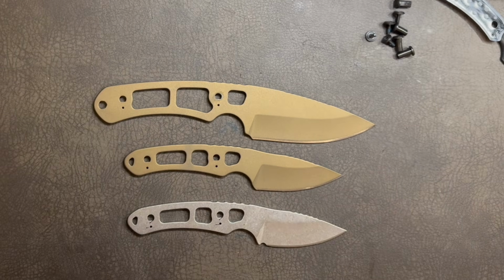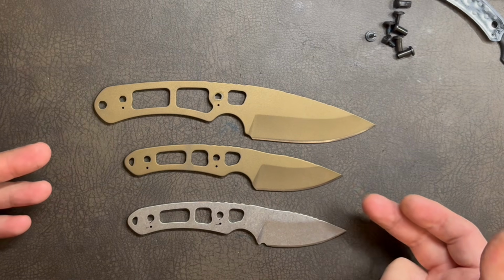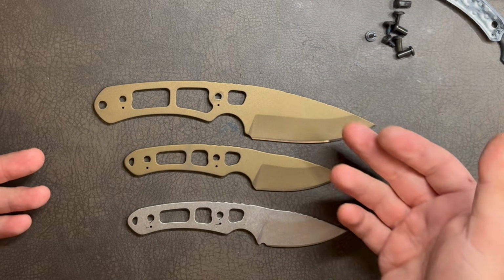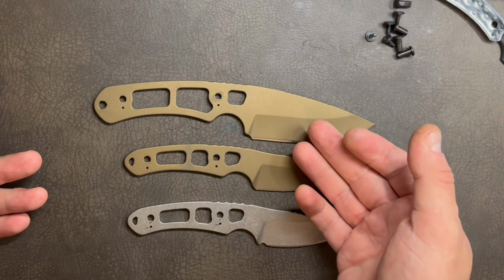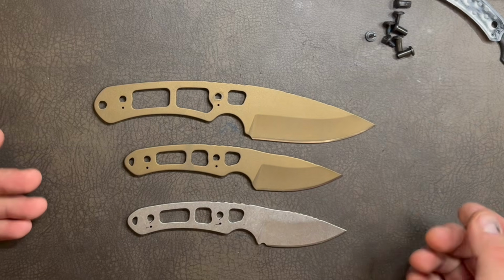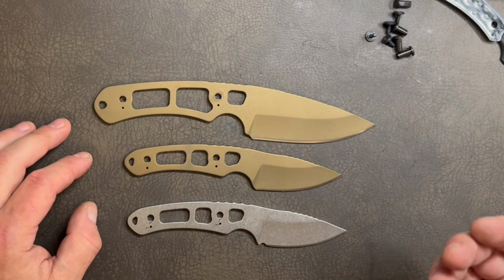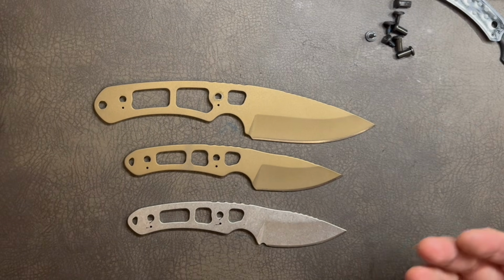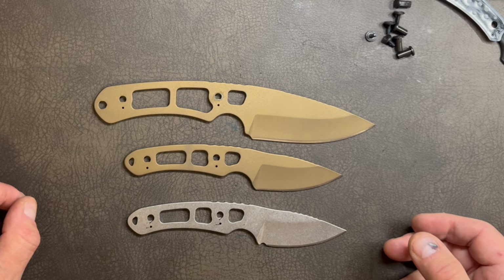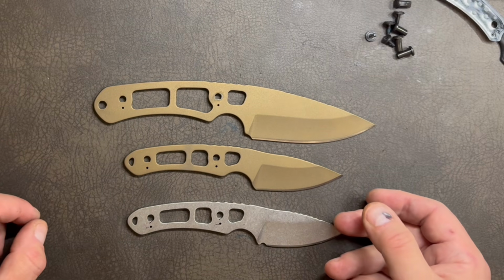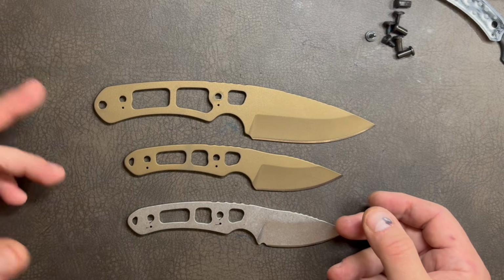Only then there comes tempering, where the blades are placed in the furnace again and heated to somewhere between 300 and 450 degrees Fahrenheit, depending on the steel, and left there for a couple of hours. After the tempering, they're again placed between the aluminum plates and allowed to cool down to 170 to 180 degrees Fahrenheit, and then if it's a good manufacturer, they'll cryogenically treat it one more time.